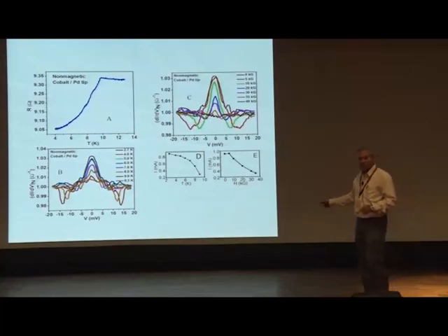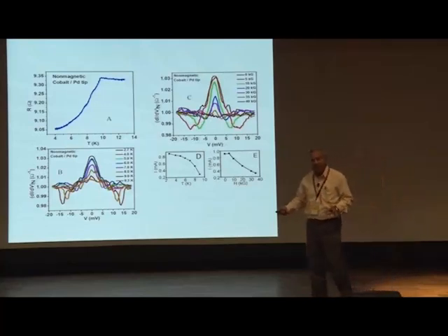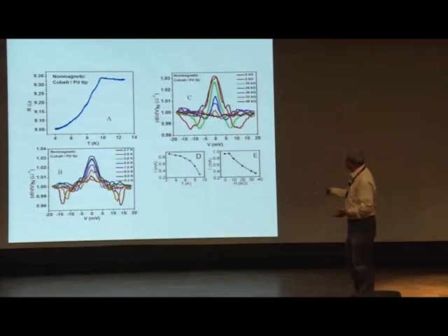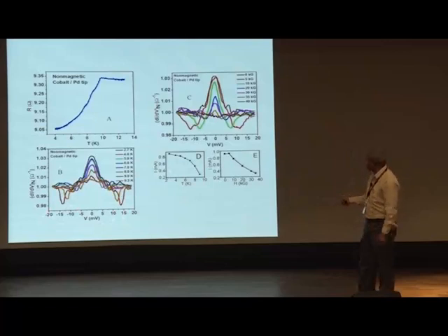This is also a feature that can come from various conditions, such as contact resistance and contact materials. It can also happen because of Josephson tunneling. We have seen that between the superconducting grains I don't have a superconducting material, so it is like a Josephson junction, and Josephson tunneling can also give you these dips. What you can derive from this is the voltage divided by normal resistance, which gives you the critical current. So this is the critical current extracted from these plots.